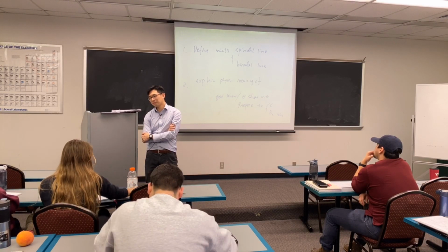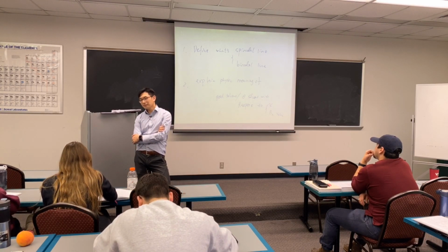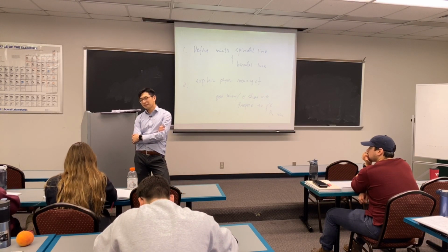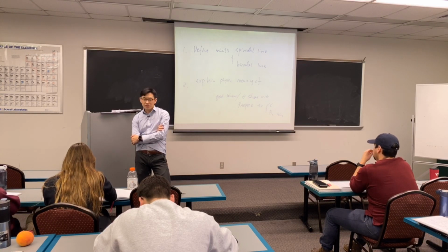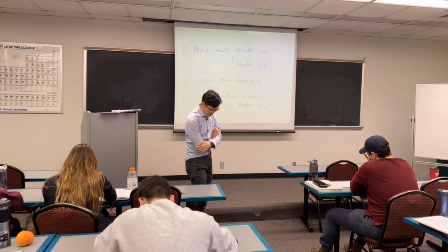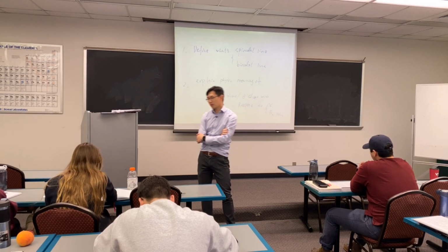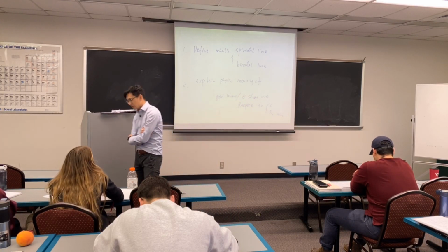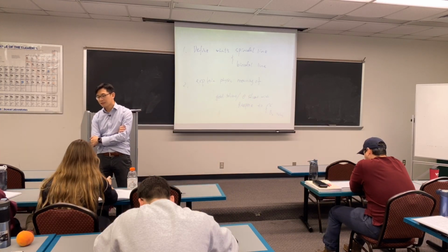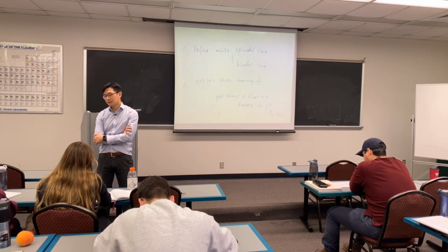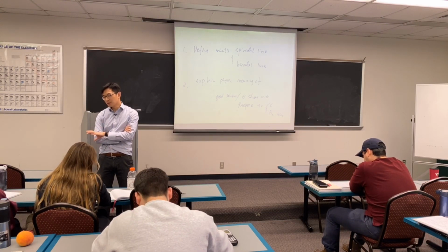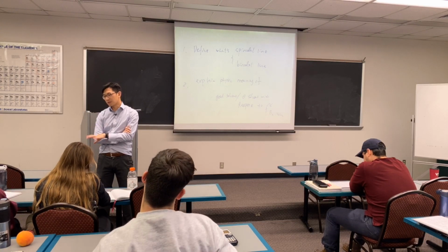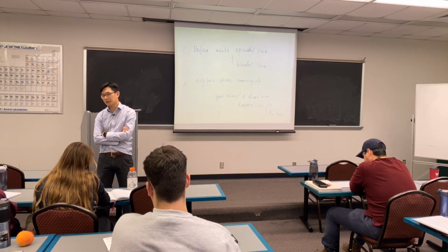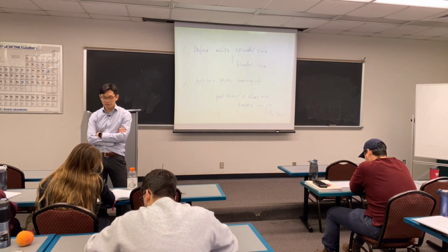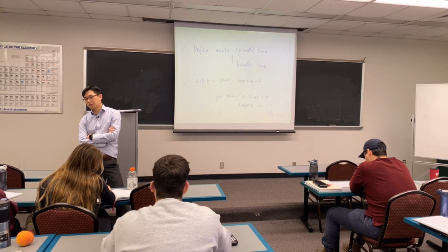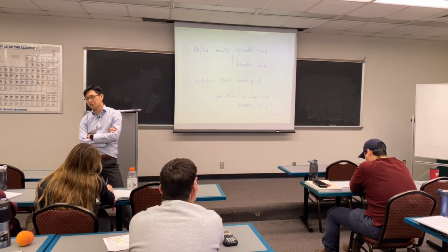So when we come to real cases, some conclusions we draw from the thermodynamic perspective are not very valid. So I wouldn't say that. This will tell you the long-term performance of your material, or the long-term thermostable states. We do need to consider the driving force, because if you think about engineering plastics, if the chi parameter is high, with time you start to phase separate and lose performance.